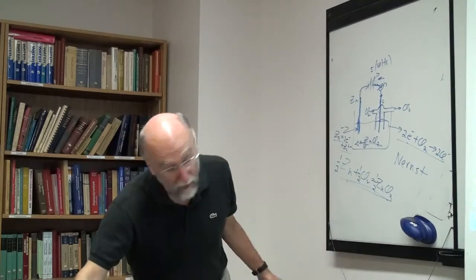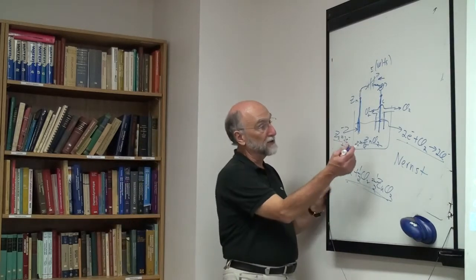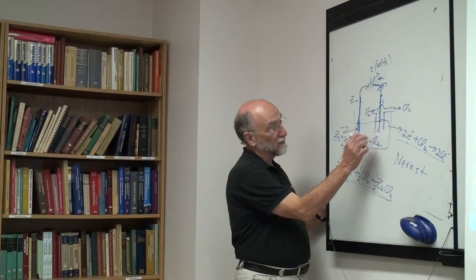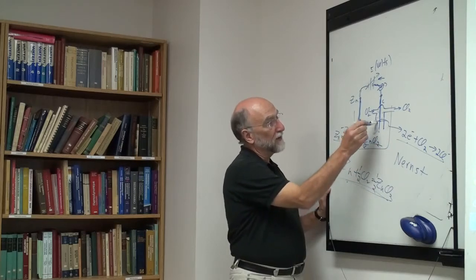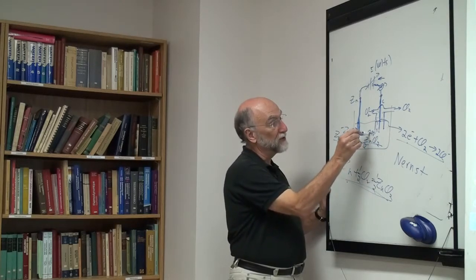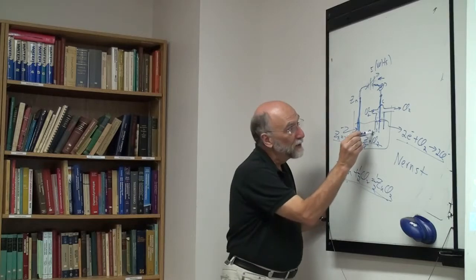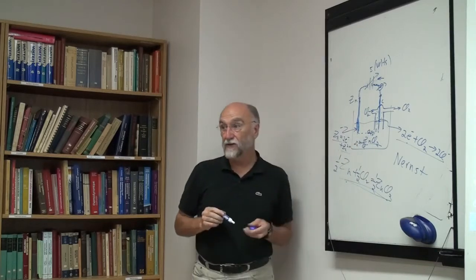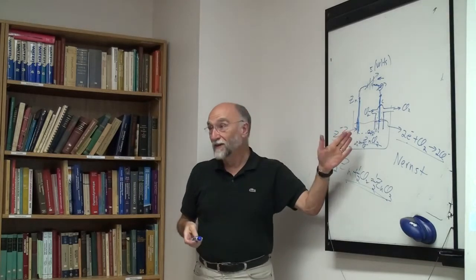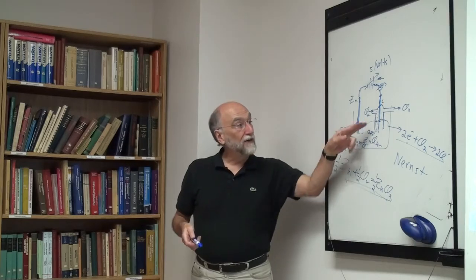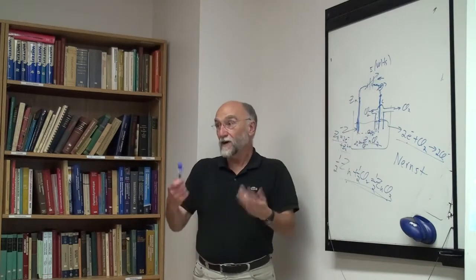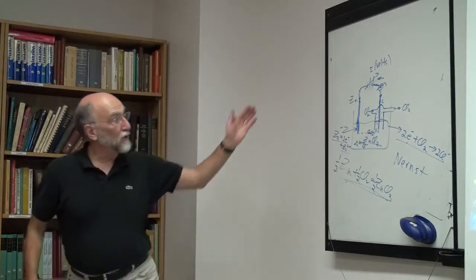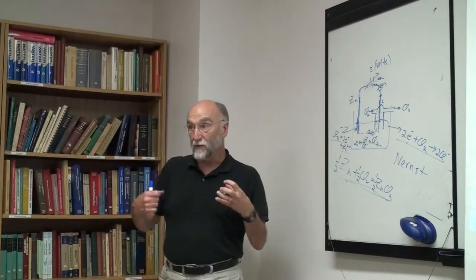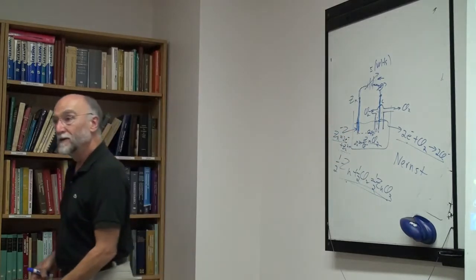The problem is, of course, that supposing now, and this is the case, in the molten salt you might find some chlorine gas dissolves in the molten salt as chlorine gas moves across and reacts directly with the zinc. In that case, of course, things aren't going to work. If the zinc and the chlorine get in contact, then no current flows, they just react chemically. They have to react only by the passage of a current. So you also have to design the cell so that this is the only way for it to occur. You must not permit any direct contact between the electrodes.